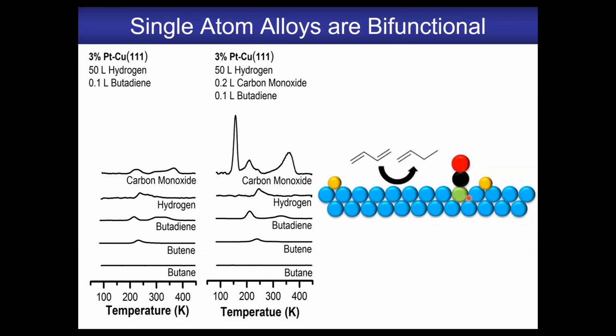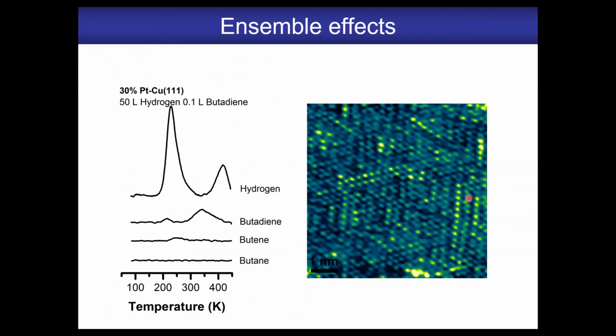And then we can address the ensemble effect again. This is an example. We've now gone up to 30% platinum on the surface. It forms these one-dimensional chains of platinum atoms. And what you can see straight away is that just by having a one-dimensional chain of platinum atoms, not even a nanocluster or anything, just a 1D chain, you've switched off your selective conversion of butadiene to butene. And you have all this liberation of high temperature hydrogen, which means you're breaking down your molecule on the surface, forming carbon. So again, the single atom alloy is an extreme example of the ensemble effect, where the single atoms will not decompose your reactants, whereas one-dimensional chains will.